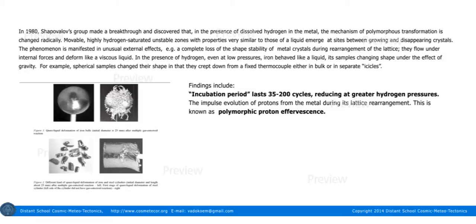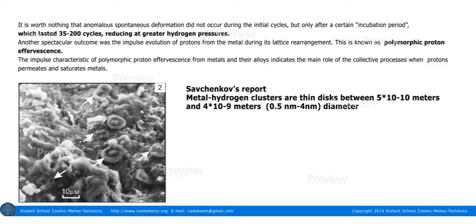In the presence of hydrogen, even at low pressures, iron behaved like a liquid, its samples changing shape under the effect of gravity. For example, spherical samples changed their shape in that they crept down from a fixed thermocouple, either in bulk or in separate icicles. It is worth noting that anomalous spontaneous deformation did not occur during the initial cycles, but only after a certain incubation period, which lasted 35 to 200 cycles, reducing at greater hydrogen pressures. Another spectacular outcome was the impulse evolution of protons from the metal during its lattice rearrangement. This is known as polymorphic proton effervescence.